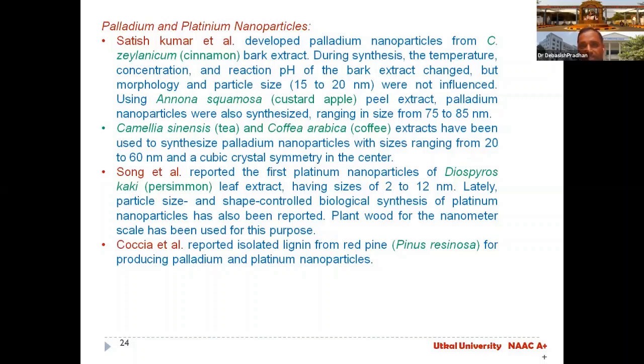During the synthesis, the temperature, concentrations, and the reaction pH of the bark extract changed, but morphology and the particle size were not influenced. You see, in that paper, it is 15 to 20 nanometer. They have established the nanoparticles, which, in my opinion, is not good to target. Okay, so these are the things.